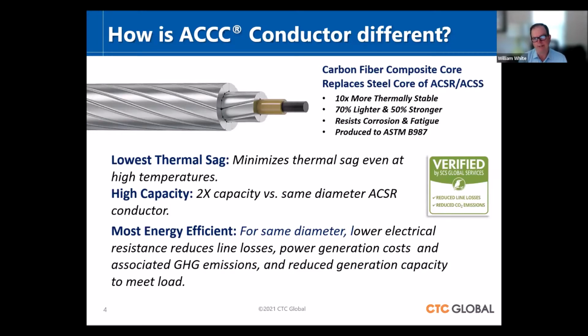And the big advantage of this is that it can run at high temperature with the same weight and the same diameter without having a clearance violation. That is something that would cause it to hit anything on the ground or vegetation underneath the line, the kinds of things that can short out the lines and interrupt electric service, but also can do things like start fires. We've seen a lot of that out in the Western United States. It's about double the capacity for the same diameter wire of the ACSR, the long-time industry standard.